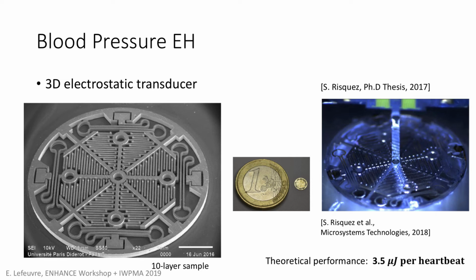So if we apply a heartbeat on this system, including the stiffness of the capsule, we estimated that the theoretical performance was about 3.5 microjoule per heartbeat net power after the circuit, with all the loss, etc. So it looked pretty acceptable for this 10-layer sample. But we couldn't show it in practice for several reasons. If you want, we can discuss about that, but we didn't get any microwatt with this device.